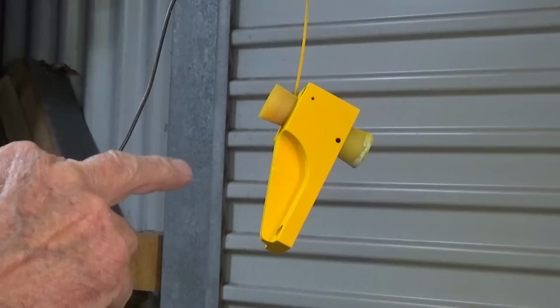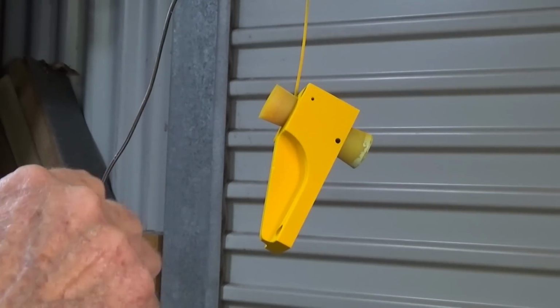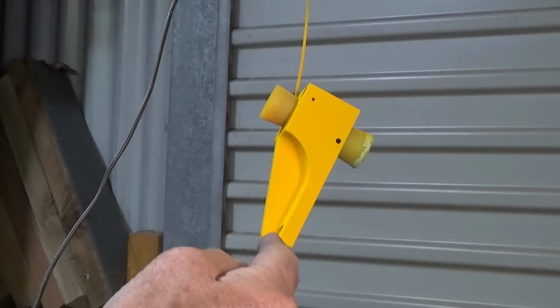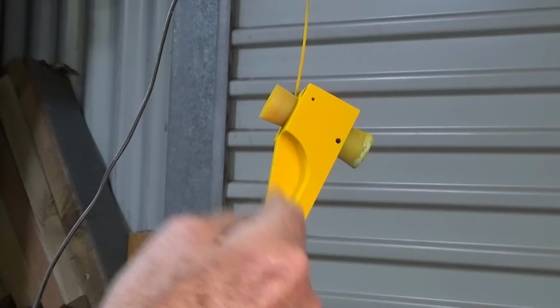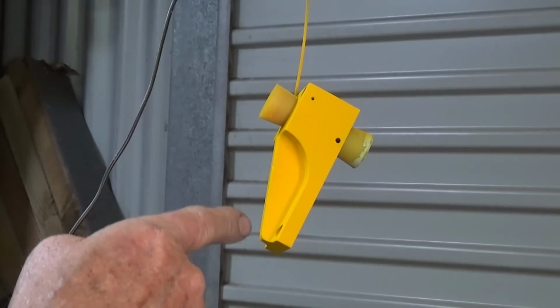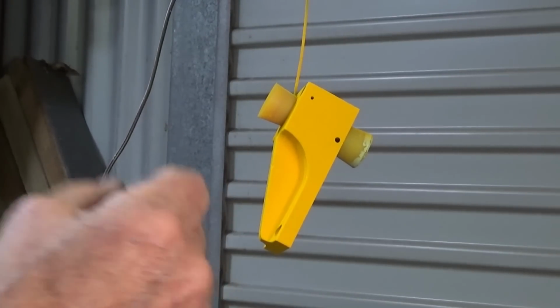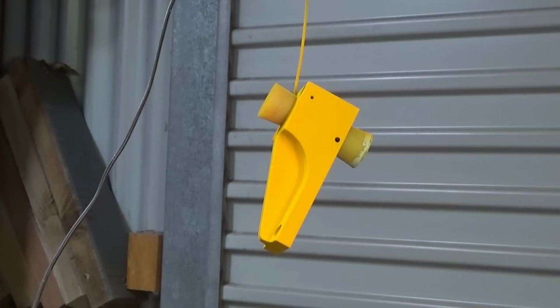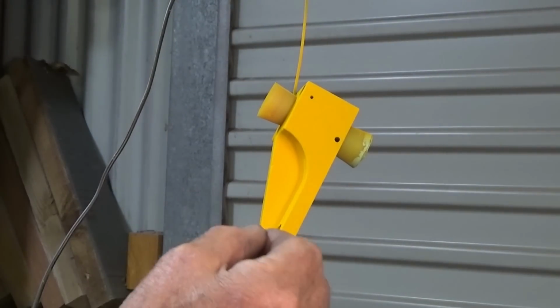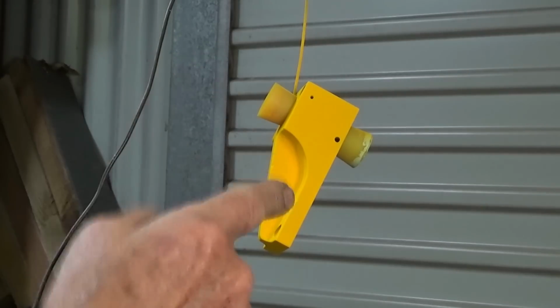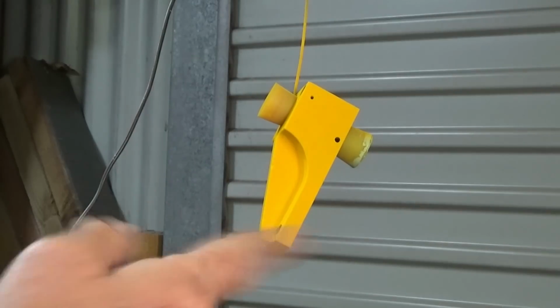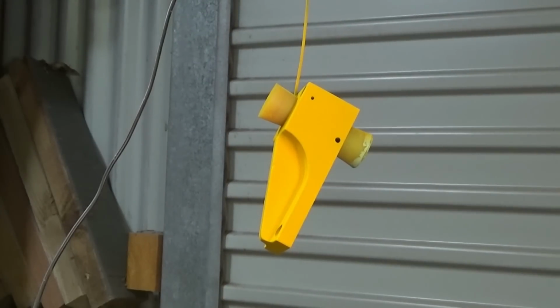You might notice there it looks a bit patchy sometimes when you first start, and what I'll often do is just zap it with the end of the gun, and that seems to put a static charge into the part, and then it accepts the powder a lot better after that. Also the powder builds up and that attracts more powder to the surface. So I'll just flip that around, give it a bit more, and get that one in the oven.